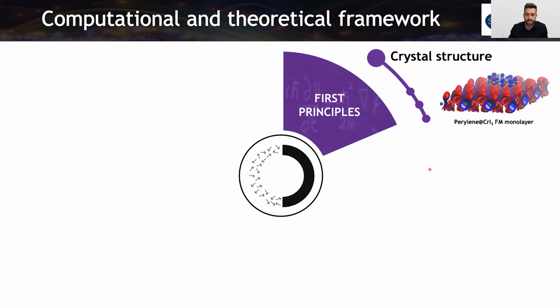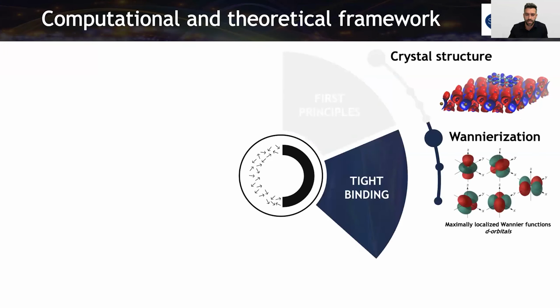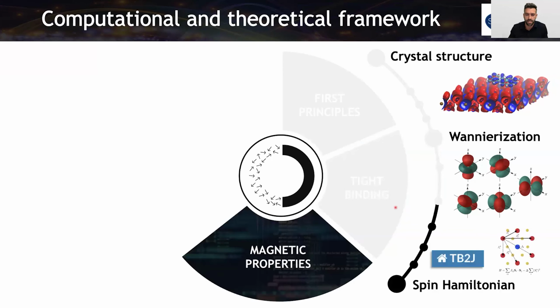So here is the computational and theoretical framework that we are using in our group. We start using first principles, density functional theory, using Hubbard corrections, because we have a strong correlation in the d orbitals. We're dealing with magnetic materials. Then we go through a process of Wannierization. So we use the Wannier90 code to obtain maximally localized Wannier functions, using, for example, in this case, the d orbital representation. And we connect with the TB2J, so from tight binding to exchange interactions to have all the magnetic interactions, the spin Hamiltonian.